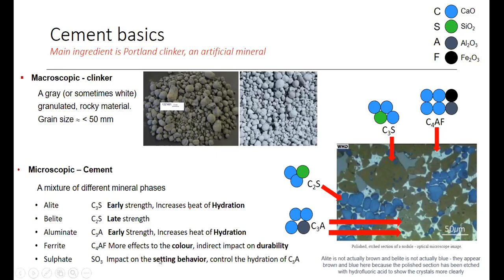And regarding sulfate: C3A is a very reactive material. If I take cement powder without adding gypsum, just by grinding the clinker and putting it into water, it will have a sudden setting. It means we will not have a sufficient amount of time to work. The workability will be very low due to the reaction kinetics, which come basically from C3A. It's a very aggressive chemical. So to reduce the reaction rate of C3A, the cement industry utilizes sulfate. Basically, the sulfate could come from natural gypsum, artificial gypsum, anhydrite, or similar materials.